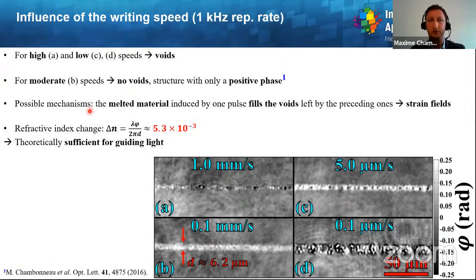The possible mechanism for this is that the melted material induced by one pulse will fill the voids left by the preceding ones, meaning that in the end, when the material resolidifies, there are strong strain fields inside the material which provoke a refractive index change. And if one wants to evaluate the refractive index change, it's given by this expression here, and we find that it's on the order of 5 times 10 to the minus 3, which is theoretically sufficient for guiding light.